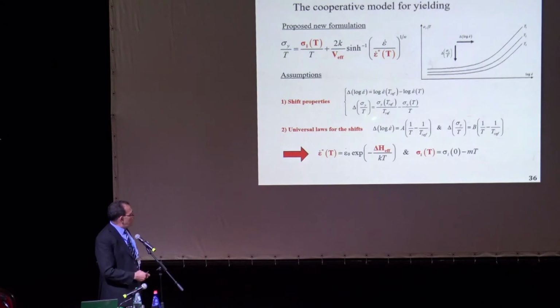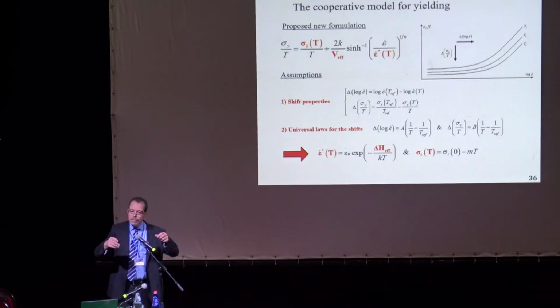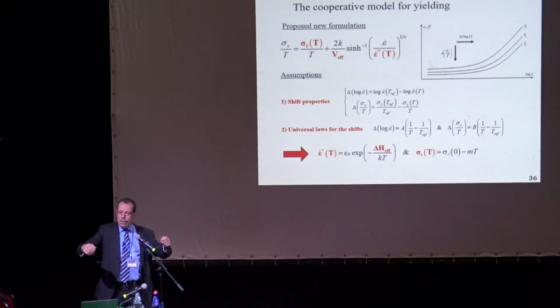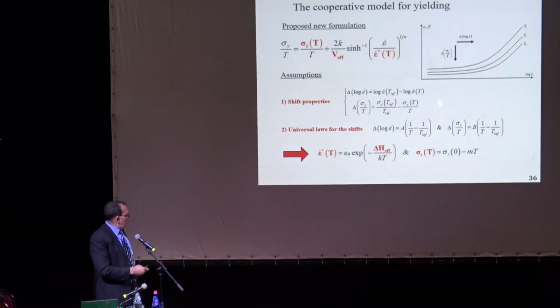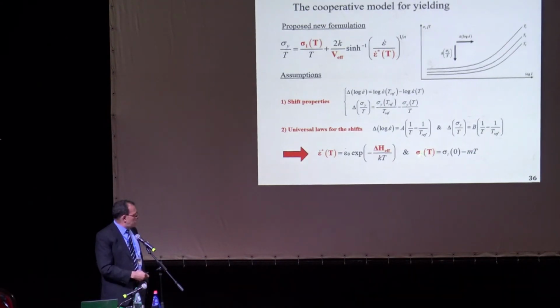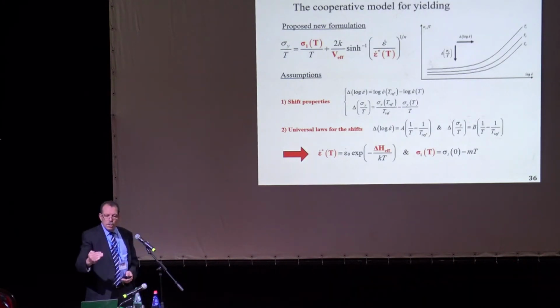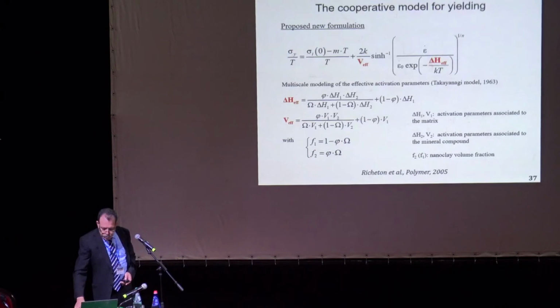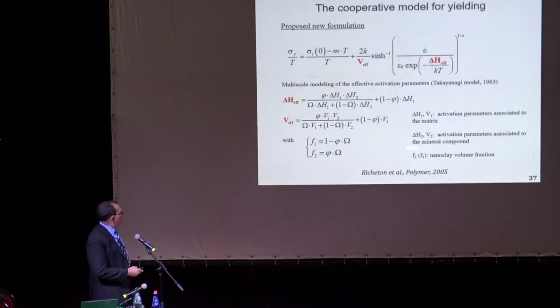The characteristic strain rate, by using shifts, in fact, what happened is the yield will shift if you change temperature, and will shift if you change the strain rate. So we use these shift relationships here, and we were able to calculate then the characteristic strain rate and link it to the activation energy, okay, and then calculate exactly how this internal stress will evolve with temperature. Okay, so it's sigma 0 minus mT. And we set it to 0 when we reach the glass transition. All right. Now this is the final relationship.